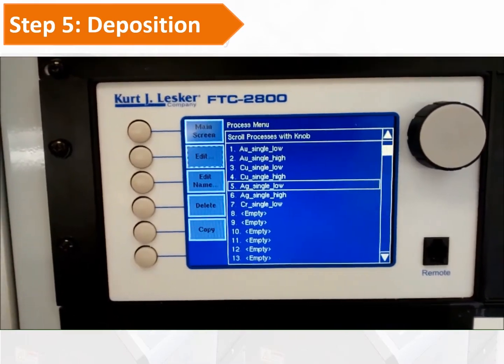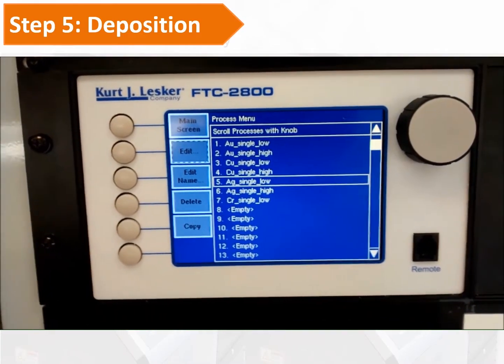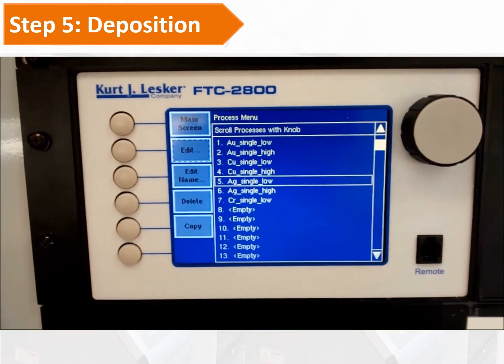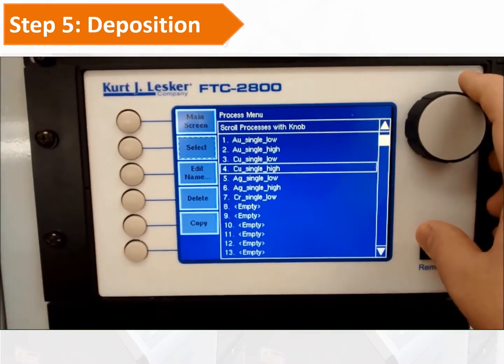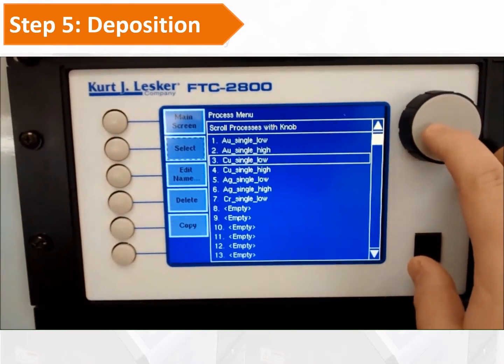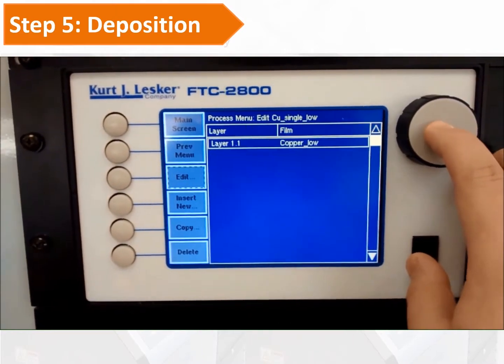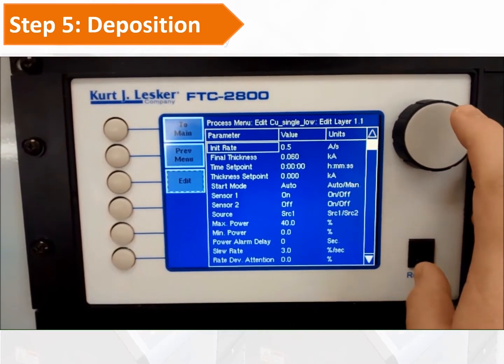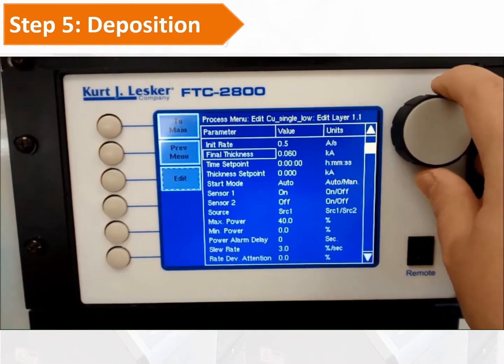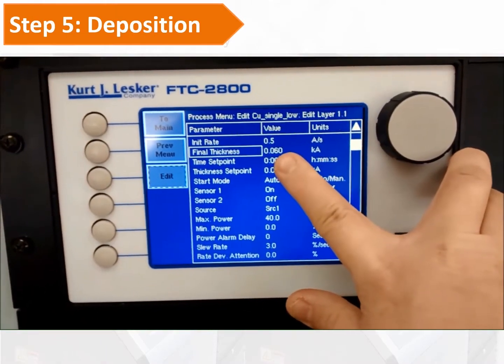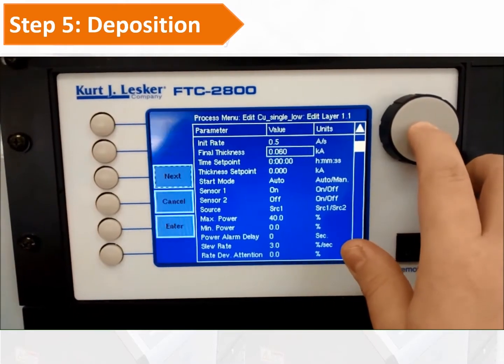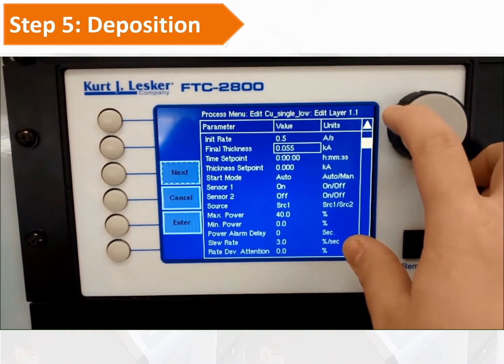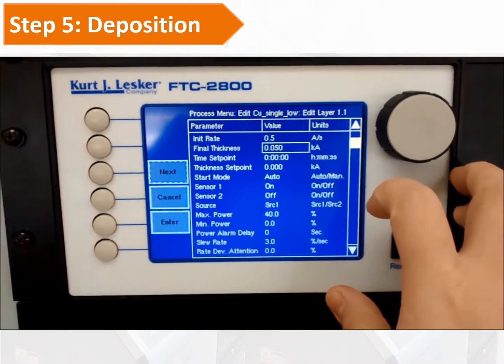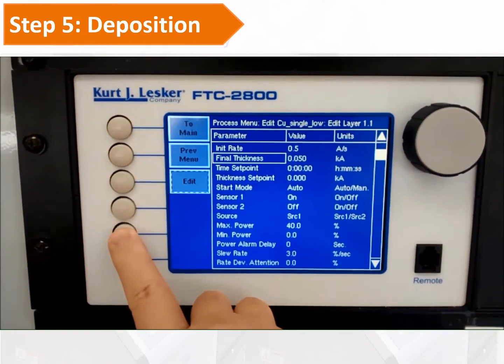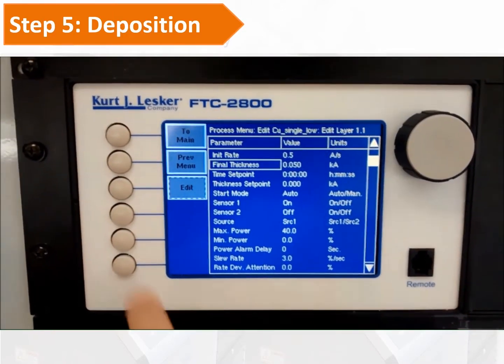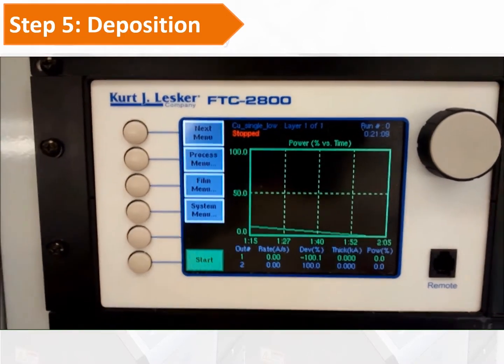If you choose a low recipe in the film menu, also choose a low recipe in the process menu. If you choose a high recipe in the film menu, also choose a high recipe in the process menu. So now we choose the copper low recipe. And then we set the final thickness to your desired thickness. Now we want to change it back to 5 nanometers. And then we press enter. And next, we can run the deposition.